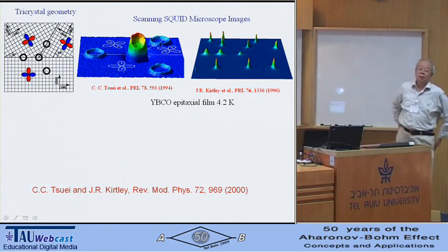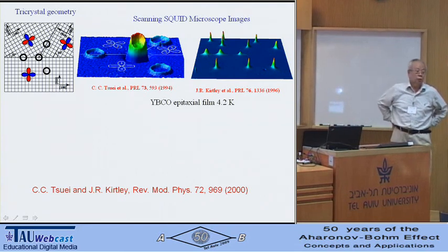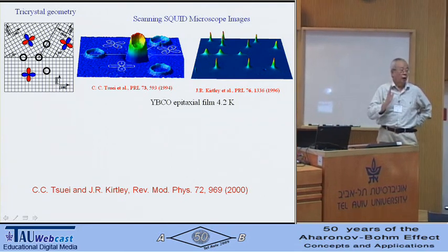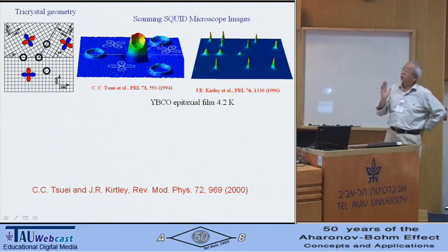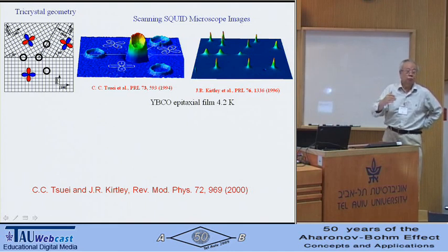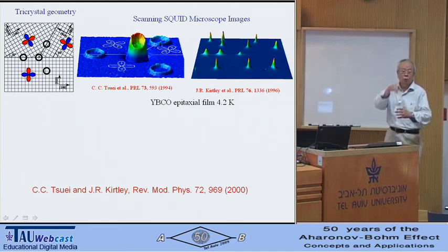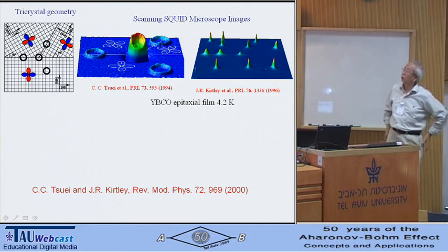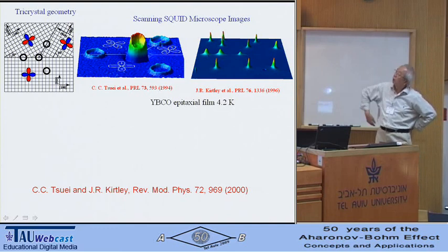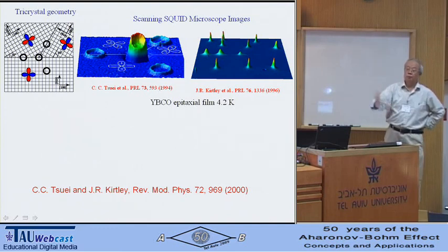You see the center. There's some signal. We calibrated. Indeed, that's a half-flux quantum. And then after that's established, you don't need to do the patterning. The patterning is kind of hard, especially making a ring right at the center of the tricrystal meeting point. Now what you do is you just deposit film.